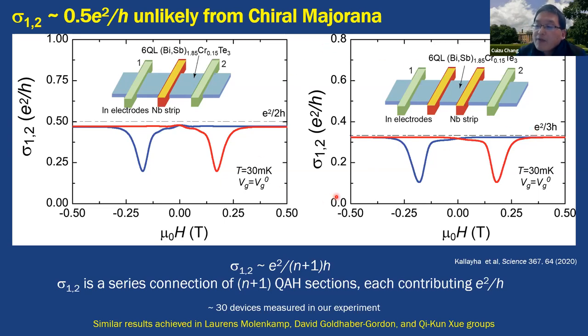So from this very simple control experiment, it shows that the e squared over 2h from this two-terminal measurement is just a series connection of the quantum anomalous Hall sections in our sample. Because if you put a Nb strip here, this side is a quantum anomalous Hall layer, and this side is also a quantum anomalous Hall layer. Each quantum anomalous Hall layer will contribute e squared over h. So two of them in series become e squared over 2h. If you put two strips, there are three parts, each one is e squared over h, and it becomes e squared over 3h two-terminal conductance.